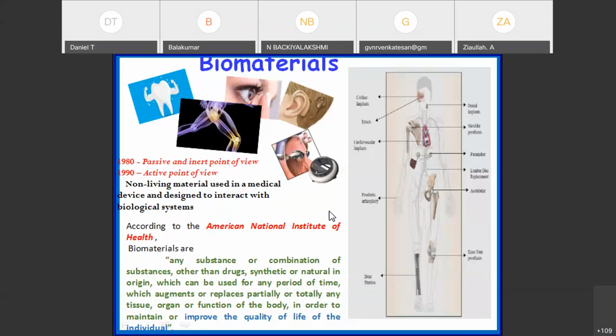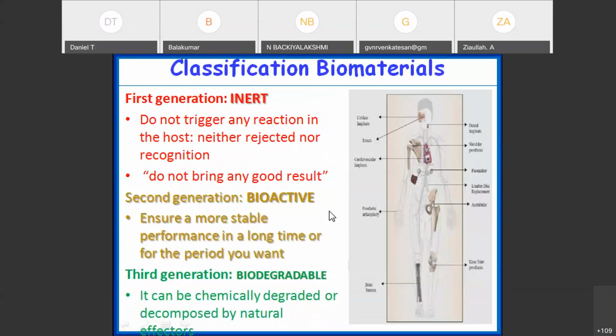Then this material is called biomaterial, but there are three different generations. In the 1980s, these materials were only used as inert material. They do not trigger any reaction. It is neither rejected nor recognized. No recognition. Do not bring any good result also. You have to keep on monitoring. In the second generation, they wanted to make this material compatible with the system. So they coated it. The coating materials are called bioactive material. This ensures more stable performance over a longer time and for the period that we require.